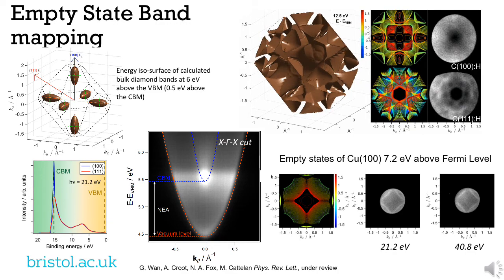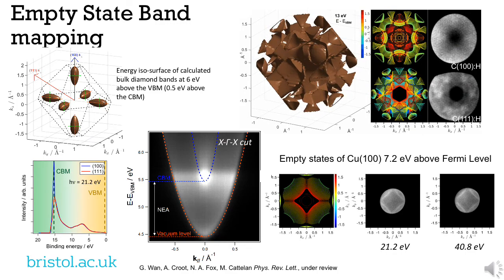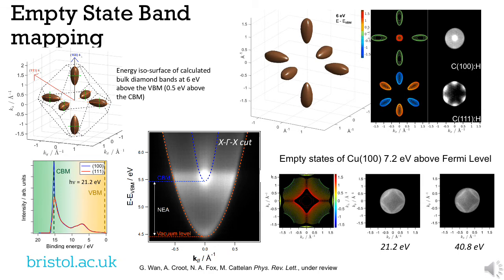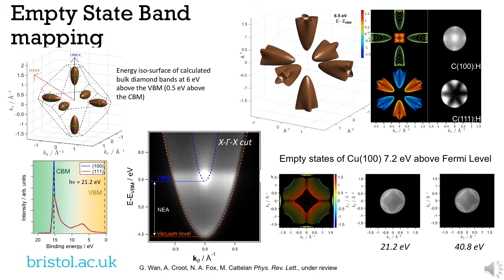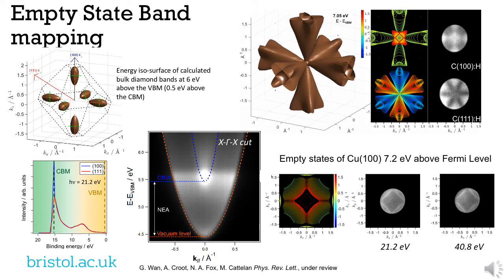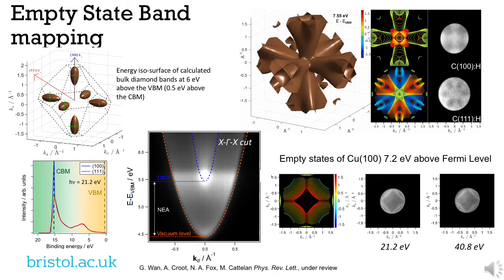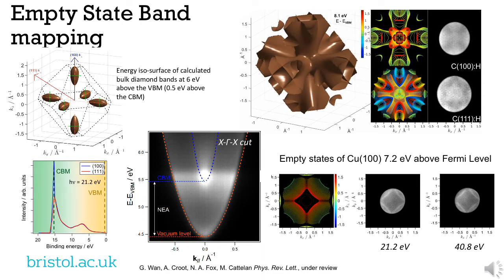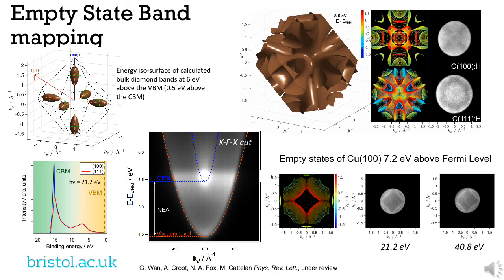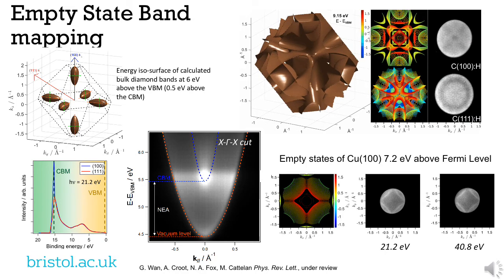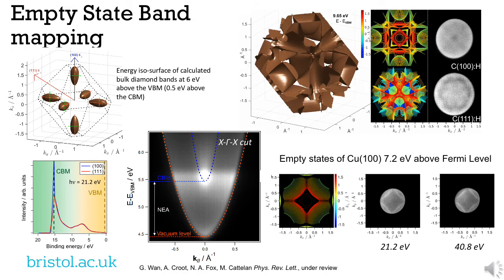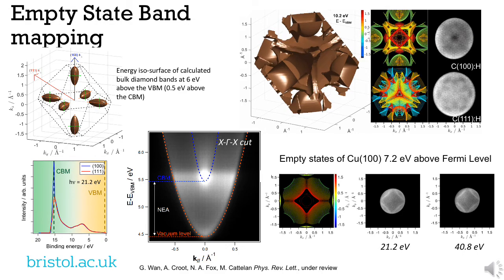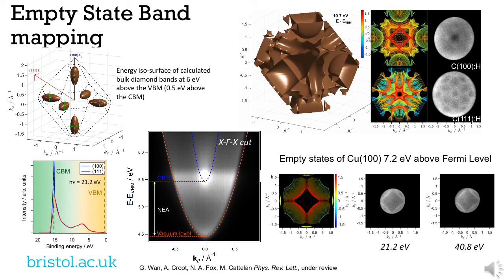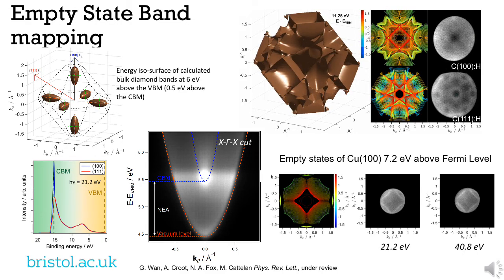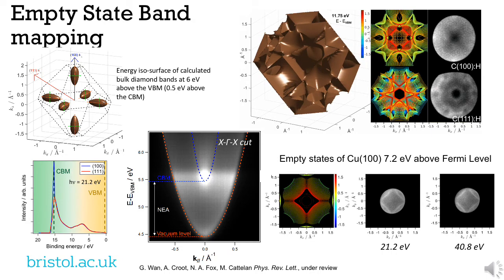structural information. However, we have used secondary electron ARPES to directly observe the conduction band of diamond up to 13 electron volts above the valence band maximum, and the empty states of copper up to 9 electron volts above the Fermi level. In this mode of emission, there is no selection in K perpendicular, but electrons still respect K parallel and energy conservation rules, as well as the energy and momentum resolution of conventional ARPES.